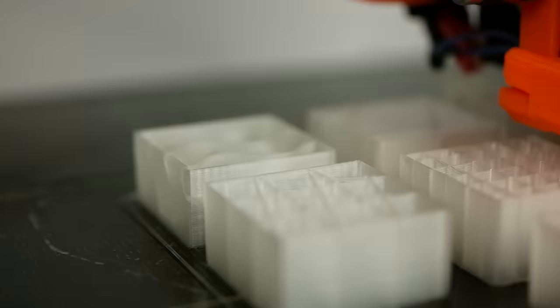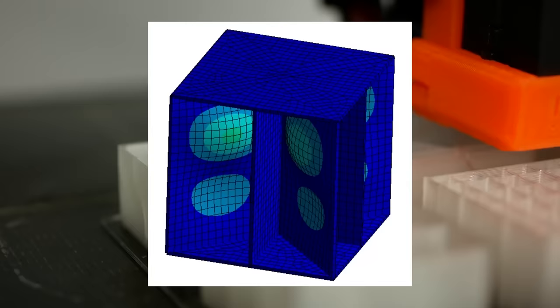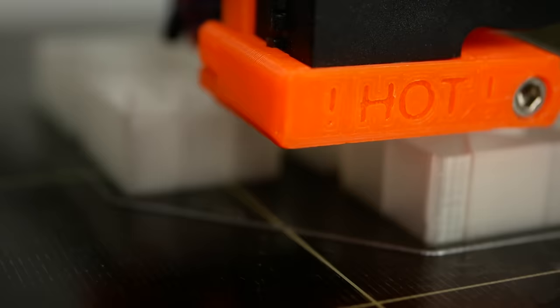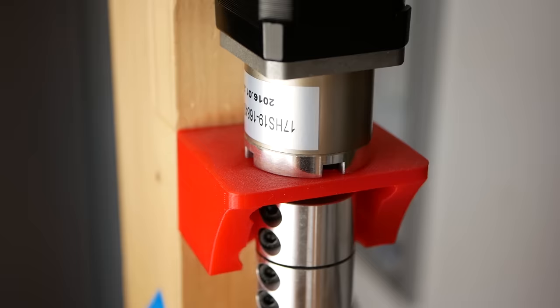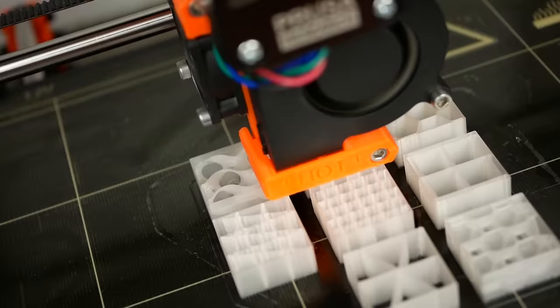The way how the parts will probably fail in such a compression test is usually not compressive yielding of the structures but the stability failure buckling of a wall which then leads to more load on the rest of the part and therefore fatal failure. The shape of the infill or even how the infill supports the external shell will determine how and at what load the structure fails. The slenderness of the structure will play a huge role and curved structures like for example in the gyroid will act like ribbing and improve the strength. I am a little bit limited on my testing machine because it unfortunately stalls at around 3.5 kN or 340 kg of load so I only used an infill ratio of 10%.